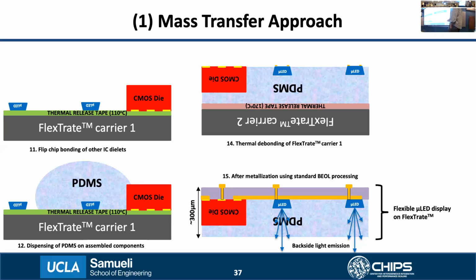The reason we use PDMS is that it has a low Young's modulus, and the drag forces produced during the curing process are very small. We can also cure it at room temperature because it has a below-room-temperature glass transition temperature. The other reason is that we use PDMS for other projects. And it's also very transparent to most wavelengths of visible light, so that's another reason. Thank you.